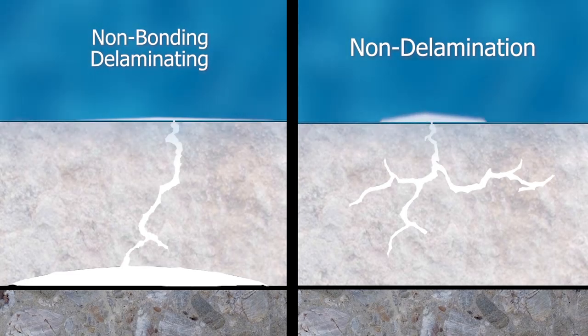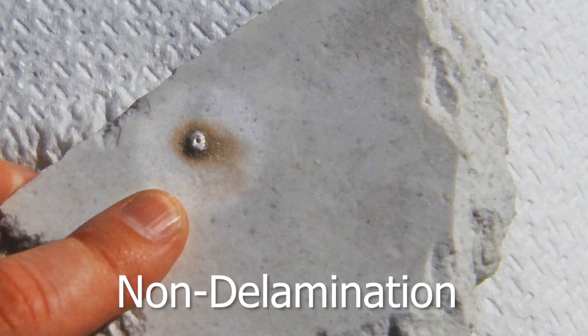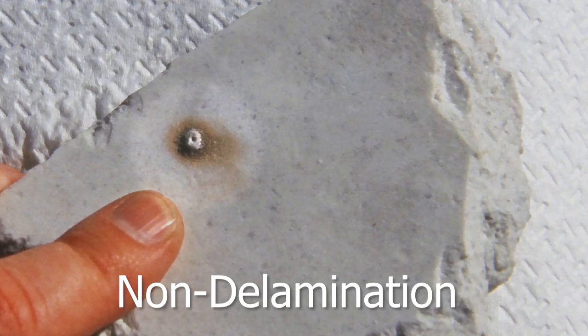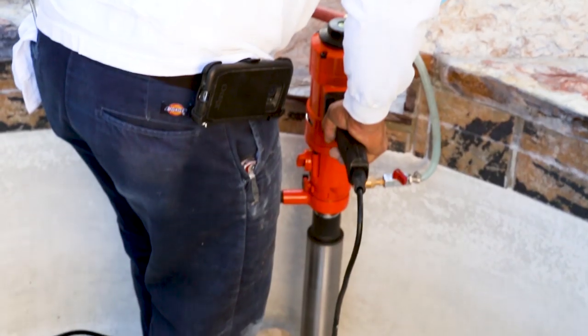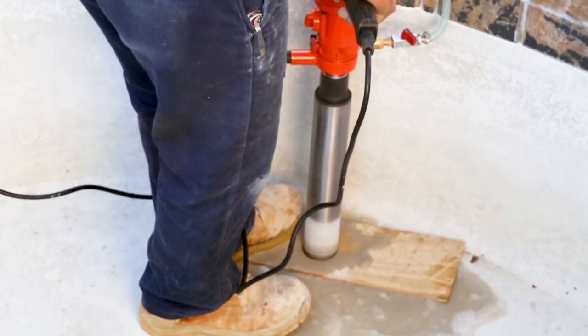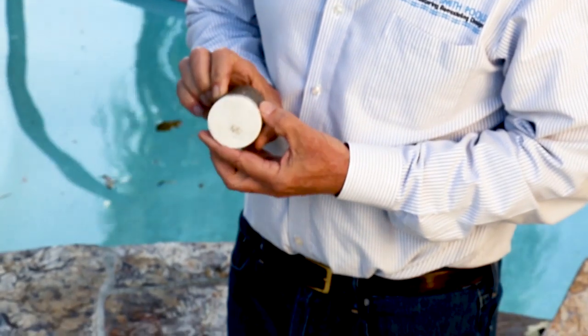In conclusion, we've learned that there are two basic types of calcium nodules that originate from two different sources. The first type, where you'll see multiple nodules within a pool surface, comes directly out of the plaster surface itself through micro cracks and micro structures filled with calcium hydroxide. Pool water that needs calcium to buffer it will simply pull it out of these micro structures and cracks and form little nodules on the surface. As you can see in this core sample, these nodules come out of plaster that is firmly attached to the gunite substrate — there is no delamination whatsoever.